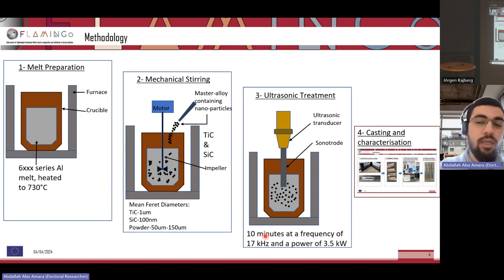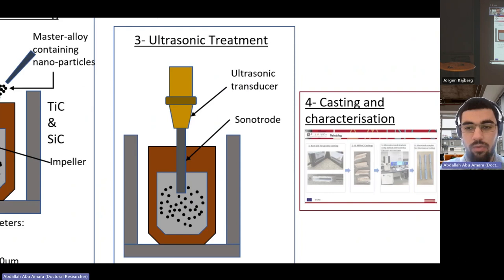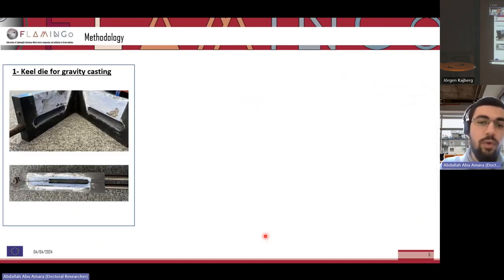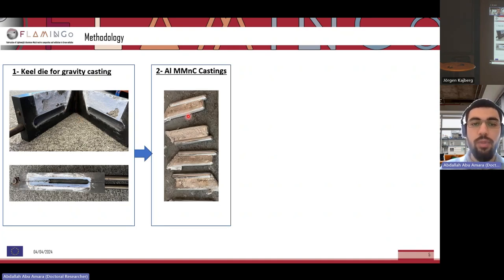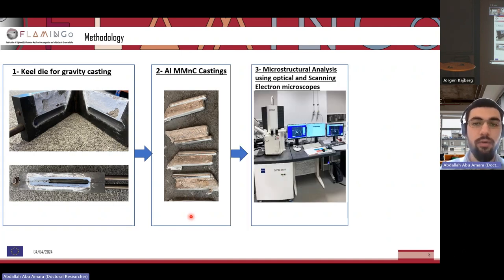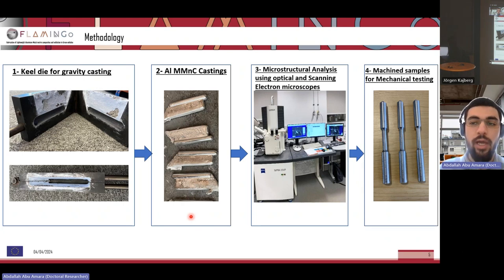And then the next step is the actual casting itself and the characterization. So let's take a look at what that looks like. So once we have the composite melt, we can pour it in this keel die, which has this shape, as you can see here. And we can produce these aluminium composite material castings. Once we have these castings, we can then characterize them using optical microscopy, SEM, XRD, and so on. And we can also machine some tensile bars for mechanical testing. So you can see it's quite convenient because we have this round section at the bottom of the die. So we can quite easily machine some tensile bars for tensile testing.